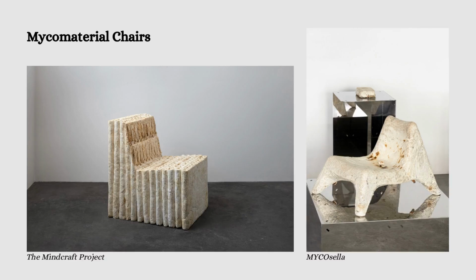So that's something you can deliberately do. You can half grow all your pieces till they start to show some myceliation, so they're not going to break apart as you move them and try to glue them together. Or you can also use some pins to keep them in place, putting the pieces together that need to fit together. But rather than using glue, you are just allowing the mycelium to grow into the other piece, which it will do. It will just glue to itself. So that's an amazing part of making myco materials. I hope I made that clear.